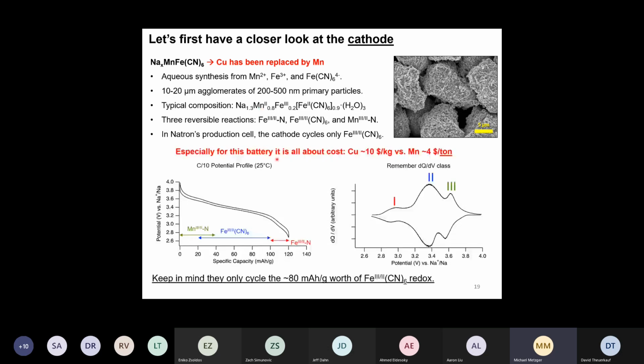So now, why did they change from copper to manganese? I think that is pretty obvious if we look at the cost of those different materials. These are very rough numbers, but copper is maybe around $10 per kilogram. Manganese you can buy by the ton, for very cheap. So especially in these batteries, which are not extremely high performing in terms of their energy density, I think it is very important that the cost is low. That's really the selling point for these batteries. So that's why it's an advantage for them to go to manganese, especially if they don't even use this redox, but only use the Fe 2+, 3+ redox.